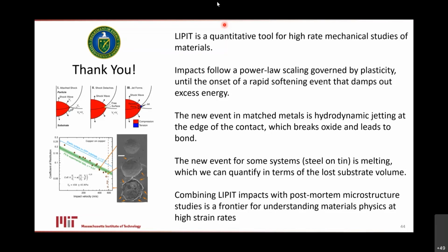So yes, the logical extension of all the things I showed you does turn out to be true. And now that we understand it, it tells you what direction to go. If you want to delay bonding or promote bonding, we definitely can fiddle with the oxide layer to help make that happen.